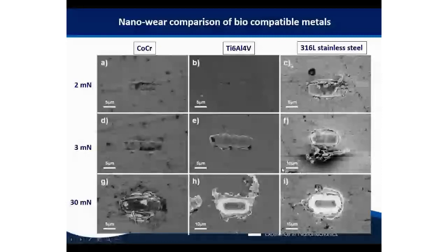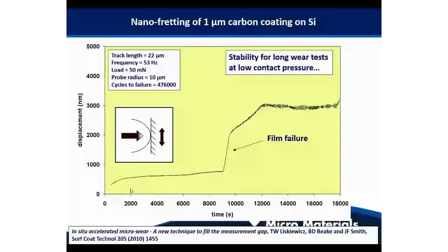So here's some example work on some biomedical alloys, and really what we're looking at here is the evolution of fretting damage that takes place in these materials at various different contact loads. The contact geometry is the same in all cases, but the way in which the debris at that interface evolves differs between the materials. So one thing that may look very good at a low level of loading may not be quite so good at a higher level of loading.